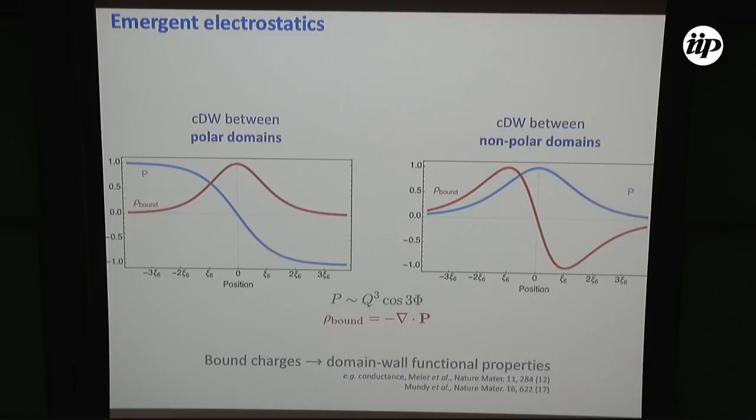So even in this case, we have domains that are non-polar, but the domain wall is a sort of ferroelectric thin film, because there emerges this spontaneous polarization localized at the domain walls. So very likely the ferroelectric domain walls in the non-polar hexagonal manganites will display new properties associated to this localized polarization, negative capacitance, or I don't know.